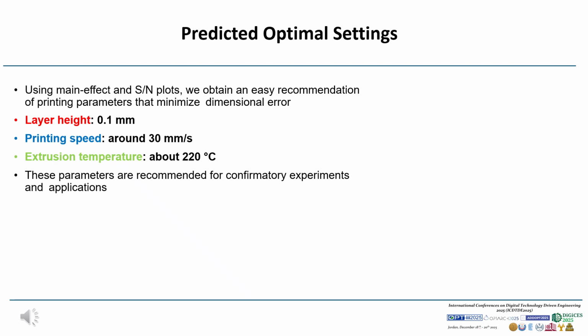By combining the information from the main effects plots and the SN analysis, we can propose a simple set of recommended settings. The optimum region for dimensional accuracy is a layer height of 0.1 mm, a relatively low printing speed of around 30 millimeters per second, and an extrusion temperature close to 220 Celsius. This combination is suggested both for future confirmation experiments and as a practical recipe for printing accurate PLA parts.